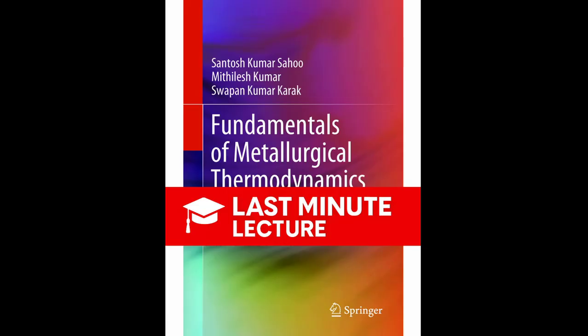All right, before we get to the final fundamental law, let's quickly cover two helpful shortcuts engineers use for quick estimates. These are empirical rules based on observation, but they're surprisingly accurate. Section 4.1 covers Richard's rule. Richard's rule is about fusion, or melting. When researchers plotted the heat of fusion against the melting temperature for different metals, they saw a pattern. The entropy change upon melting, delta S_m, which is delta H_m over T_m, is roughly constant. It falls in the range of about 8 to 17 joules per Kelvin mole. So if you know the melting point of a metal, you can quickly estimate the heat needed to melt it. It's a good first guess when you don't have precise data.